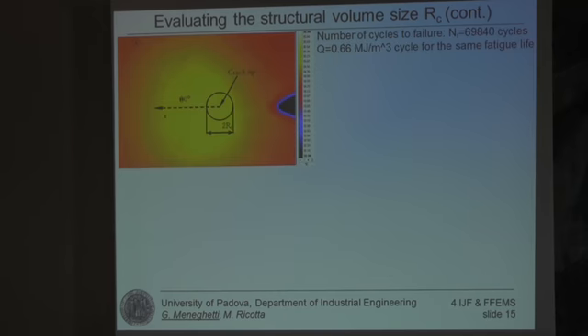Now, if we go back to our cracked specimen, we have its life, we have the characteristic energy for that life. So the problem is to find the structural volume size such that the average of the energy inside that volume is 0.66 megajoule per cubic meter. This was the procedure, and we could conclude that the size of the structural volume is 0.65 millimeters.